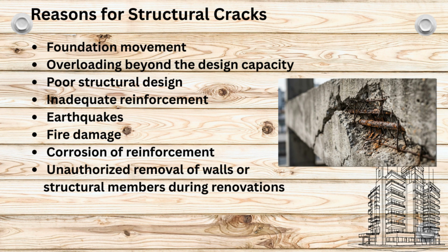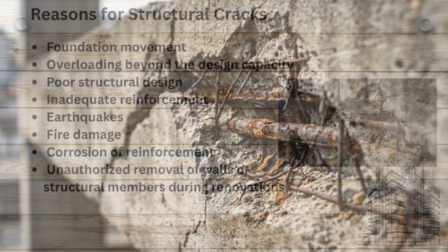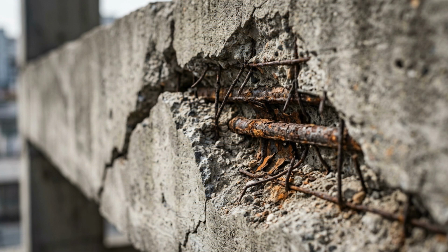One of the biggest concerns is reinforcement corrosion. When water enters structural concrete through cracks, it eventually reaches the reinforcing steel. Steel begins to rust, and rust occupies much more volume than the original steel. As the rust expands, it pushes against the surrounding concrete, creating larger cracks and causing pieces of concrete to break away, a process known as concrete spalling. If this deterioration continues, the structural strength of the member gradually reduces. For this reason, structural cracks should never be ignored.